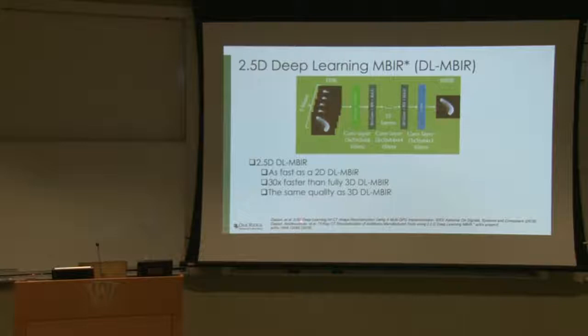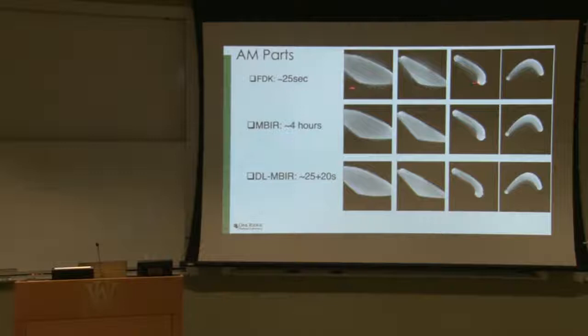So here is an example of the same jet engine turbine part scanned in an X-ray CT system. And here is the standard filtered back projection, in this case, FDK, because it's a cone beam system. You're looking at cross sections from a 3D object, okay? Using a simple algorithm, using the model-based method, which in this case is just an implementation, so I wouldn't take this number as the most optimized piece of code, but it still takes a lot of time. You get improvements in quality, whereas if you use a deep network which has been trained to map from here to here, you can get the answer really fast for a huge volume. You're looking at getting an answer in 45 or 50 seconds.